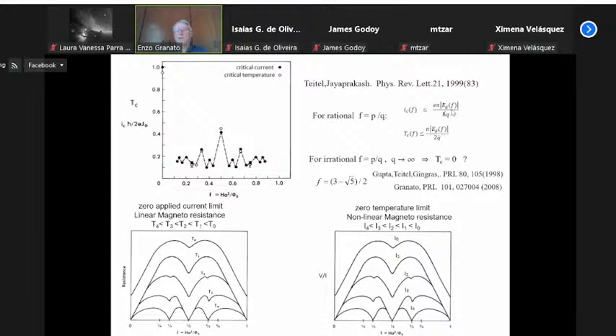Since the ground state energy, although it depends on f, depends only weakly on f, this relation shows that the critical current and the critical temperature strongly depend on the denominator of the rational number which describes the frustration. It is strongly dependent on the rationality of this frustration parameter. In particular, if you have a rational number represented by a fraction with a very large q, tending to 0, this equation suggests that the critical temperature vanishes for a rational number.